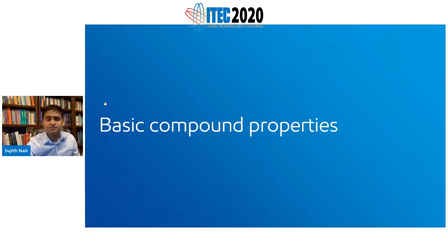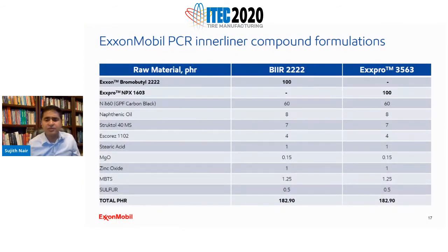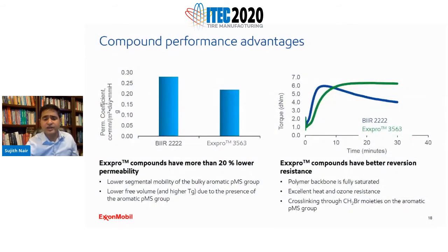And that's possible too. So let's look at some of the basic compound properties that we have between Exxpro and bromobutyl. We use a standard ExxonMobil formulation, use 60 parts of black, 8 parts of oil, 7 parts of resin, 4 parts of the tackifier. And in this case, we have used similar curing systems. It's a zinc oxide, MBTS, stearic acid, sulfur-based cure that we have used. But again, as I said, you can cure it fully sulfur-free. You can use resins to cure it. If you want to speed up the cure a little bit, there are multiple ways to actually do that.